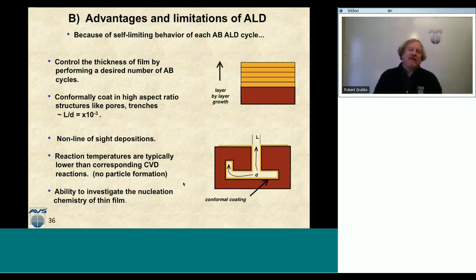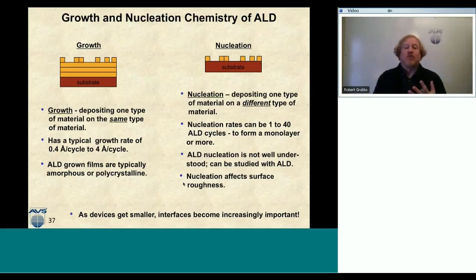With that, what motivates this slide is that everything I've talked about is really growth. I've talked about depositing one material on the same type of material, and that's why I had you assume that there were these oxide handles on the surface, because that was our reactive handle on the surface. And so when we talk about growth, we already assume that the ALD chemistry can take place. As I mentioned, typical growth rates can be like 0.4 of an angstrom per cycle, up to 4 angstroms per cycle, depending on the chemistry. ALD films are typically amorphous or polycrystalline.